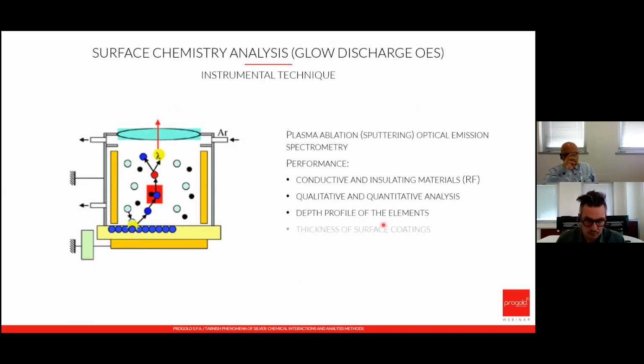After all these treatments or sample preparation, the chemical analysis was performed using glow discharge optical emission spectrometry, which uses an argon plasma as atomic exciting source like the ICP technique, and at the same time for sputtering and probing into the depth, like a sort of three-dimensional analyzer. This technique is capable, for instance, of a sputtering rate of about 700 nanometer per second and a sampling depth of 5 to 50,000 nanometer, or if you prefer, 50 micrometer. But unfortunately, it is a technique not sensitive to molecules.